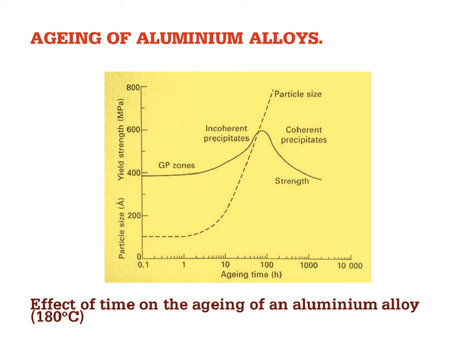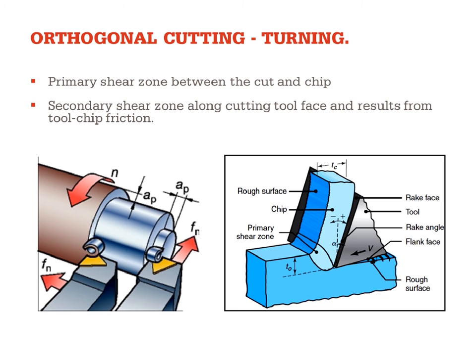at 180, the particle size increases and increases and increases. The solid line, starting at 400, shows the strength of the material. As the particles increase in size, the strength goes up, and then we reach a peak, and if we continue to age for too long, the particles become too large and the strength decreases again. So a heat treater would understand this and would know what combination of time and temperature to use to get the optimum strength of his material. And again, that's covered in great depth in the aluminium training courses that we offer.